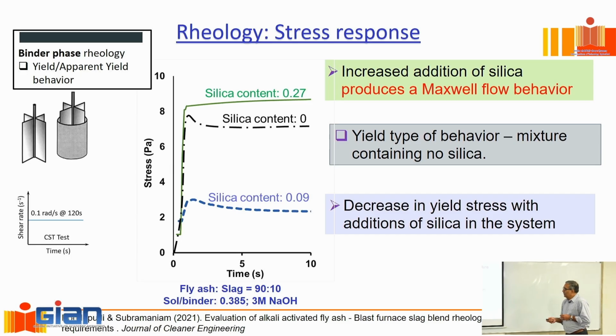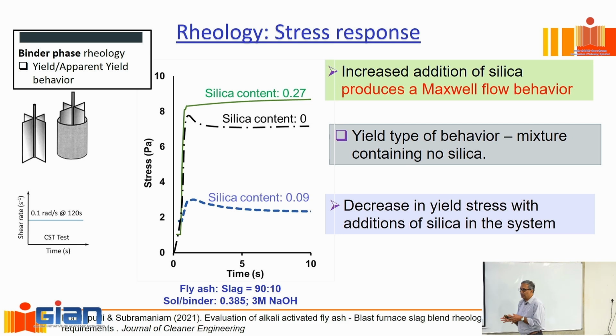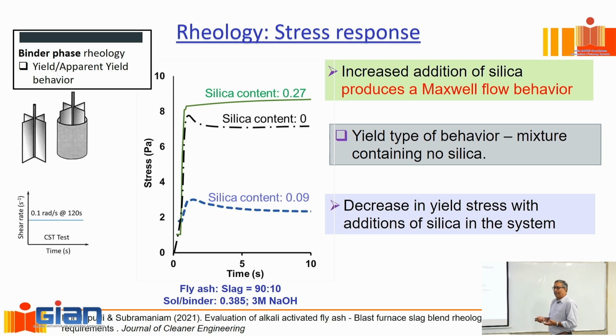See what happens. When the silica content is 0, which means I am just adding sodium hydroxide to the paste, you get something that we are all used to seeing. Basically, the stress builds up. This is the yield stress. Then you get flow here. Right? Why do I call it a flow? Look at this. The resistance here has become a constant. I've sheared it off and now it's flowing at a constant resistance. Right? Look what happens when I add some silica. The yield stress actually decreases. Okay. So what is silica doing? Silica is actually at some level decreasing the viscosity, but doesn't stop there. Look what happens when I add more silica. It bounces back. So why do you think that happens?